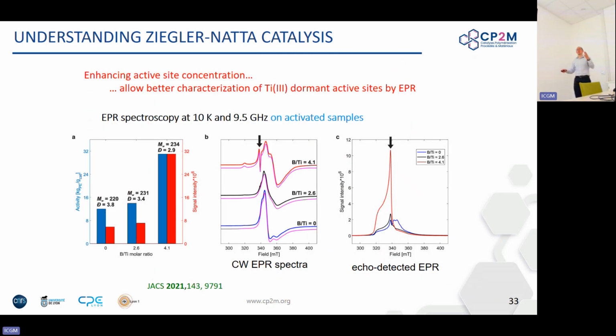You can also, if you follow a reduction pathway, a titanium 4 will become a titanium 3, and this you can follow by EPR, and this is what we did. So by EPR, we observed by increasing the amount of BCl3, ranging from 0 up to 4.1, we saw the appearance of a titanium 3 species, and by doing 2D EPR, we were able to realize that this is characteristic of the titanium 3 dormant site for Ziegler-Natta.